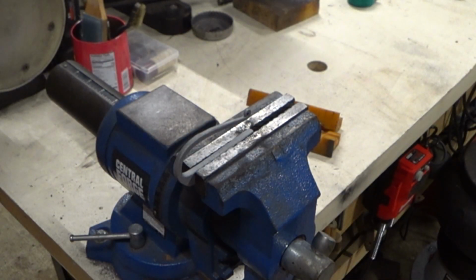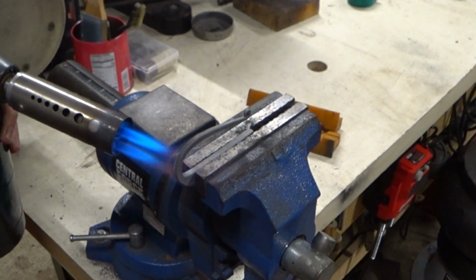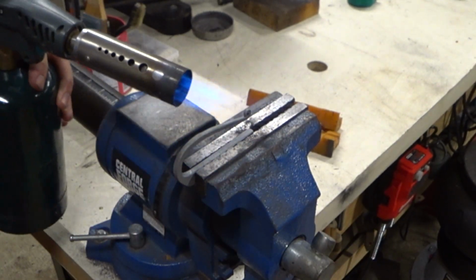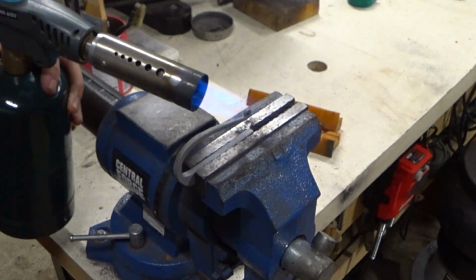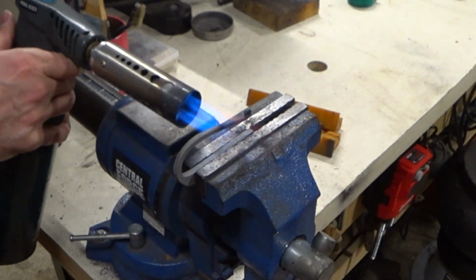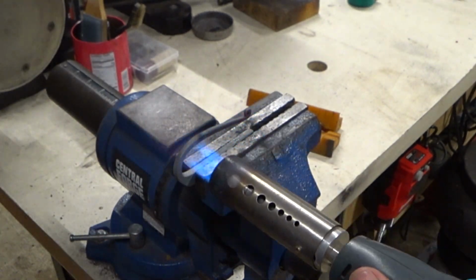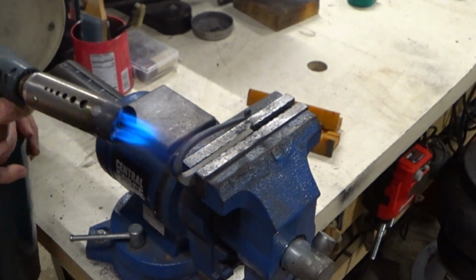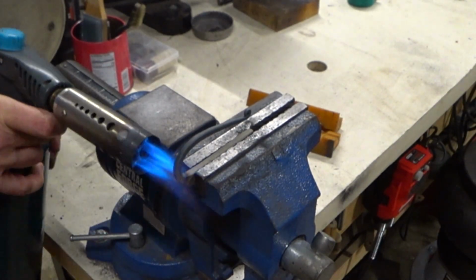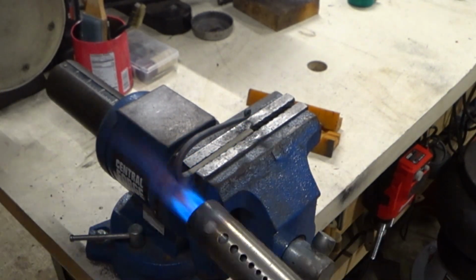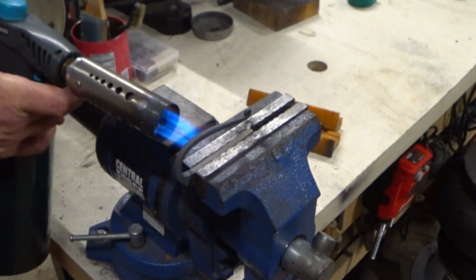Even after a light temper, the handle is going to be kind of brittle because it's such a thin piece of material. So I usually clamp the main body into the vise so it doesn't get tempered any further, and then I use a torch to temper the handle all the way back. This way it will bend rather than break if it's subjected to any abuse.